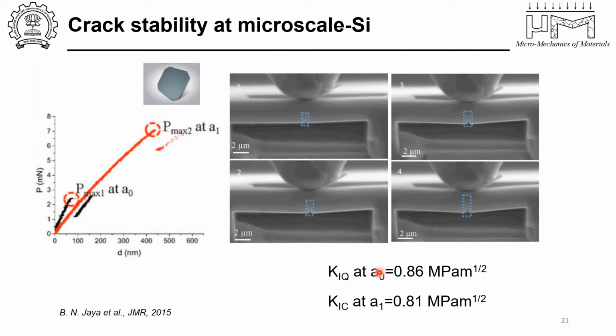Corresponding to that, we measured a fracture toughness of 0.86 MPa√m. We reloaded the sample. Now it loads at a lower stiffness, but it takes up a higher load before it finally breaks. And the corresponding fracture toughness is 0.81. So there is not much difference in the fracture toughness at the different crack lengths that you see. Again, not expected for silicon. It's a monolithic material whose fracture toughness should remain the same.